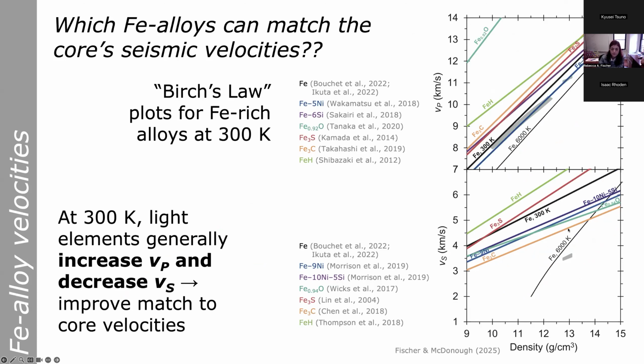We can make the same kind of plots for various iron light element binary materials. So now the black curve is for iron at 300 K, and all the colored lines are for different iron binary compounds also at 300 K from a bunch of different studies. And what we can see, at least at 300 K, is that adding light elements to iron generally has the tendency of increasing VP and decreasing VS, which is the right direction to improve the match to the velocities of the Earth's core. But it's hard to put an exact number on it the way we could with the density, for a variety of reasons.